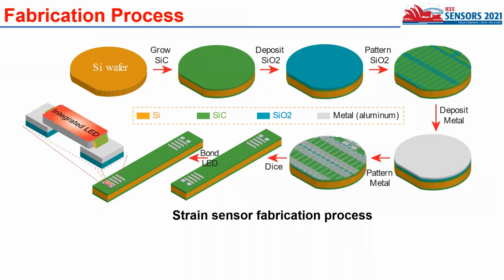To investigate the performance of the sensor, the first step is to fabricate the sensor. This slide shows the fabrication process of the strain sensor. The first process is to grow silicon carbide on a silicon wafer, and the second is to deposit and pattern the silicon dioxide on the silicon carbide layer, and after that, deposit and pattern the metal electrode on the